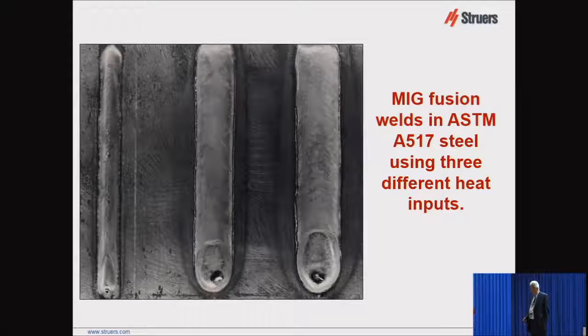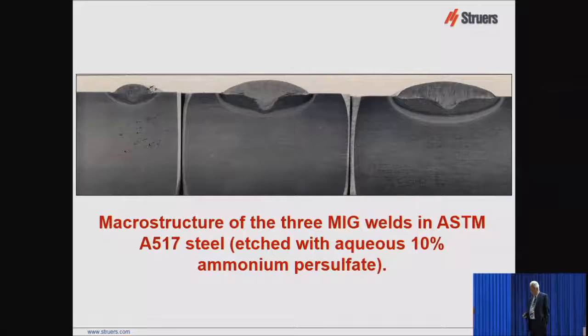This is an aerial view, so to speak, of MIG metal inert gas fusion welds in ASTM A517 steel. We're using three different heat inputs, and obviously this is the highest. Here's the end of the weld, and here's the intermediate, and here's the lowest. And when we look at these in cross section, and this unfortunately had a little debris on the sample when it was photographed, but you can see the patterns that are created.